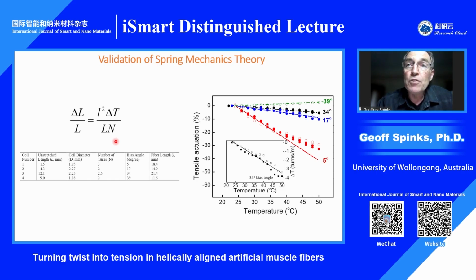To check this spring mechanics applicability, we twisted some nylon fishing line, and then we made that twisted fiber into different shaped coils. So we had different lengths, different diameters, different bias angles, and so on. And then we heated and cooled those coils and measured their length change, which is plotted here on the right. You can see we're just heating over a relatively small range and measuring the tensile actuation as a percentage of the starting length. Negative means contraction. The symbols are the measured results. The solid ones are for heating, and the unfilled symbols are for cooling. And the dashed lines are predictions made from this spring mechanics equation.